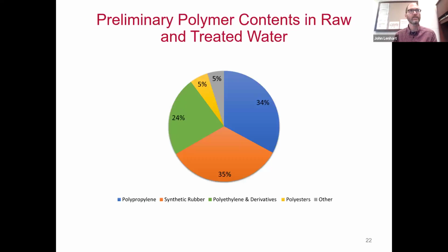Last bit of results here. This is some of our results looking at the different plastic types that we've identified, and this is a compilation of raw and treated water. What we see is that the particles are dominated by 3 particle types. We see polypropylene, that's the blue up here. We see polyethylene and derivatives of polyethylene, that's this green, 24%. One thing that we're still struggling with, because it hasn't been reported very much, is a fair amount of synthetic rubbers.